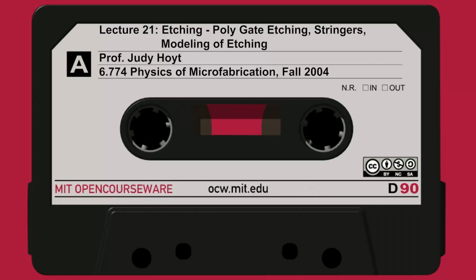So let's look at slide 17. This is an example on that paper, that article from IBM, on the effects of topography on gate conductor yield with respect to shorting. As I mentioned, if you end up with stringers, the gate can be shorted to the source and drain. So here's an example, and they etched here 21 wafers or so, 20 wafers, and the percent yield. So if you have a high yield, it means you don't have gate to source drain shorts. If you have a low yield, it means you have shorts between the gate and the source drain.